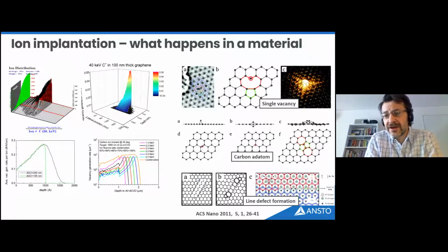We utilize ions. One great property of ions is that they have a very well defined range in the material. What you can see on the left side is the ion distribution of 40 keV carbon ions being implanted in a graphene oxide membrane, for example. You can see that the peak of the distribution is around 100 nanometers. By modifying the energy of the ion, we modify the penetration depth, or the depth at which we modify the material. So this is a great property of ions.